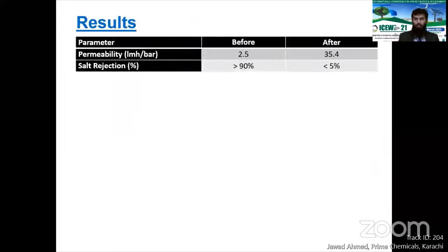Proceeding towards the results, these are summarized here in the form of membrane permeability. We can see that before the conversion process, the membrane permeability was 2.5 LMH per bar, and after the removal of the polyamide layer, the membrane permeability increased over 10-fold to 35.4 LMH per bar. The salt rejection, which was higher than 90%, was reduced to less than 5%, confirming the membrane conversion to ultrafiltration from reverse osmosis.